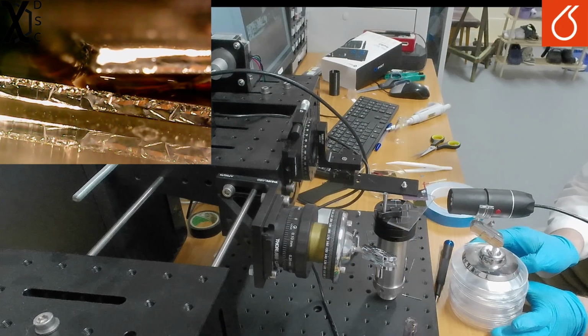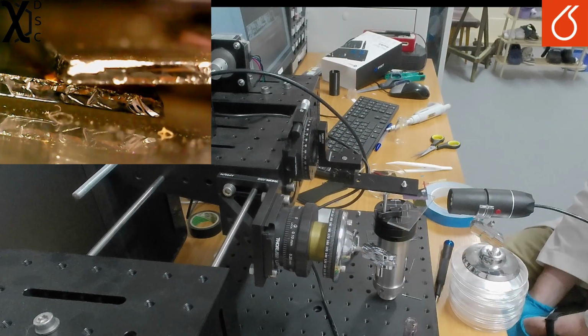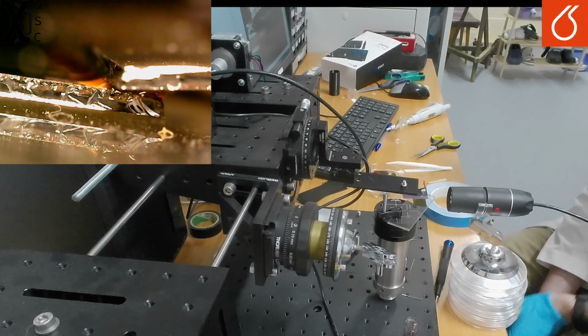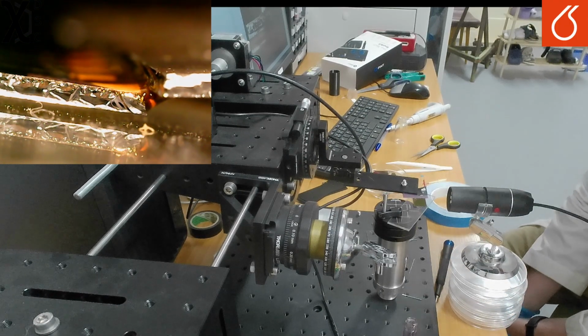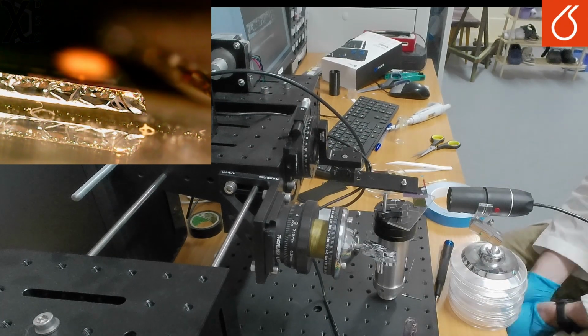I'm using 10 mg per ml of P3HT in toluene and adding 15 microliters. Currently there appears to be some problems with this method. It is suspected it is related to the surface tension of toluene, causing banding in the deposition. I am still troubleshooting this.